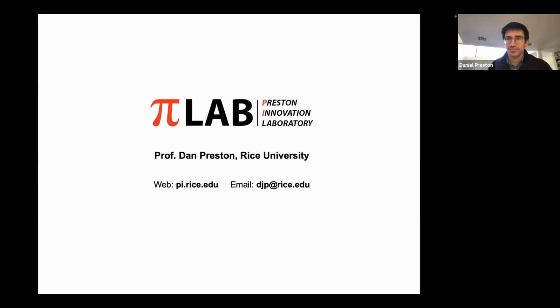Yes. Okay, so the question I have is, if you use dielectric fluids such as Novec fluids or similar products, those fluids are known to be highly wetting, and someone also calls them cleaning fluids. So I wonder whether you guys had the chance to look into the effect of contamination for that class of fluids? I do not recall having looked at this as part of that collaborative work. And I would guess that it does a great job of eliminating the source of error. As you mentioned, they're very highly wetting. Even if we have some contamination on the surface, probably our contact angle is still essentially 0 degrees. I don't imagine that we have any difference in the thermal resistance due to some thin contamination layer. So I would guess that for the boiling performance, it should probably be essentially the same, whether it's contaminated or not.